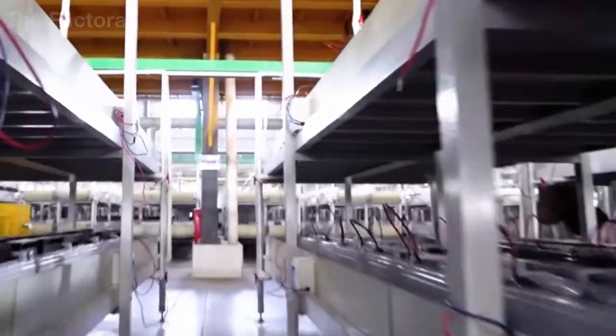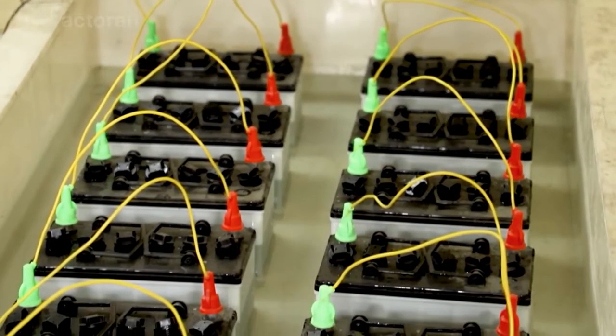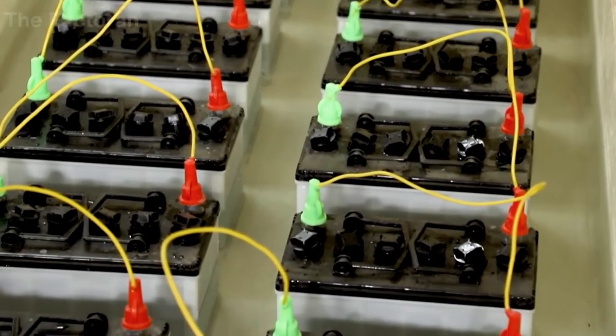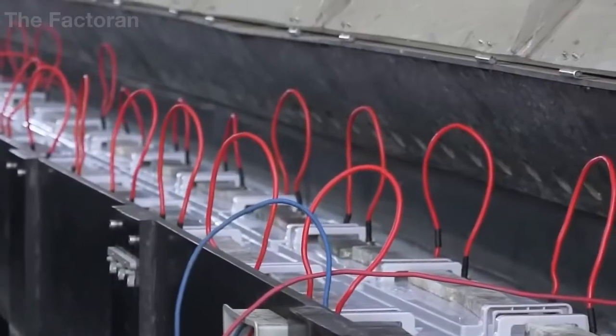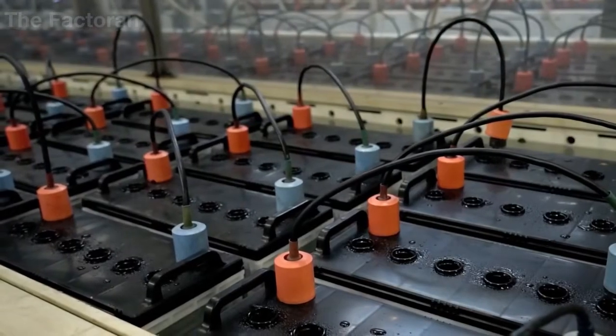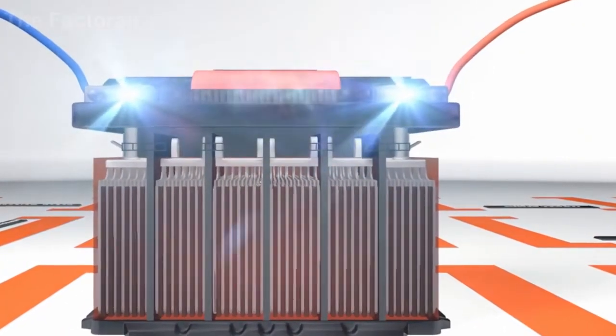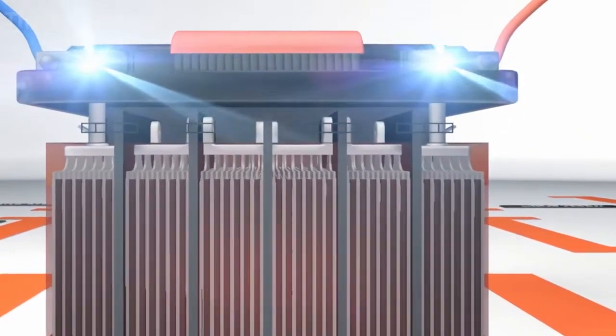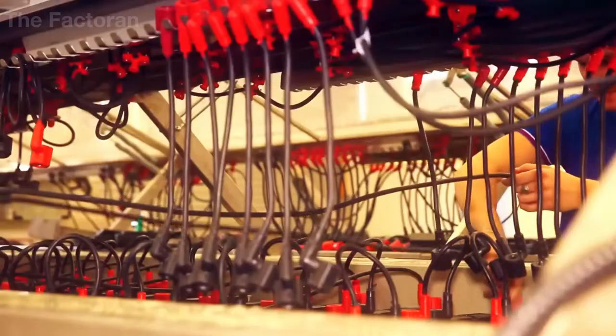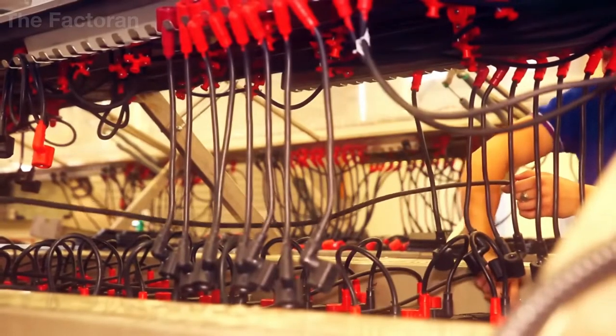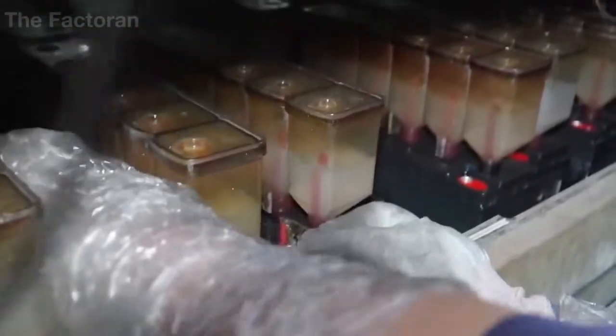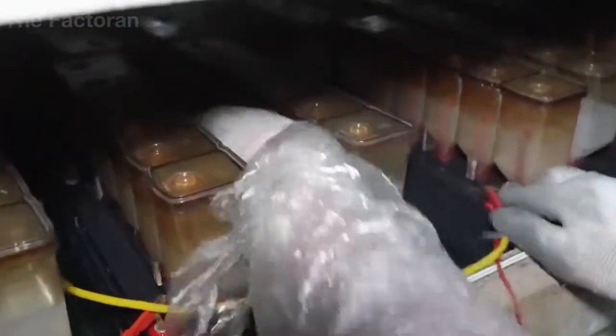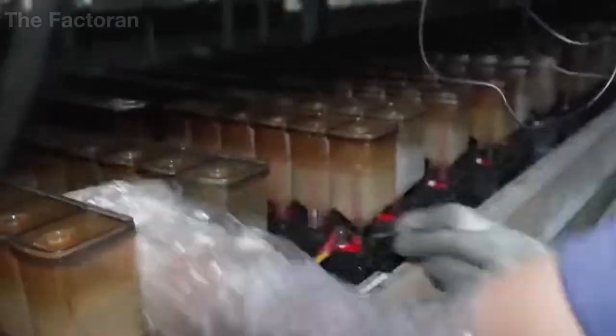Under the intense effect of the direct current, the electrolyte begins to bubble vigorously, driving powerful electrochemical reactions inside each compartment. The transformation begins. The inert lead oxide at the positive plate is converted into dark brown lead dioxide, PbO2, while the paste at the negative plate is transformed into porous metallic lead, Pb, with a gray-silver appearance.